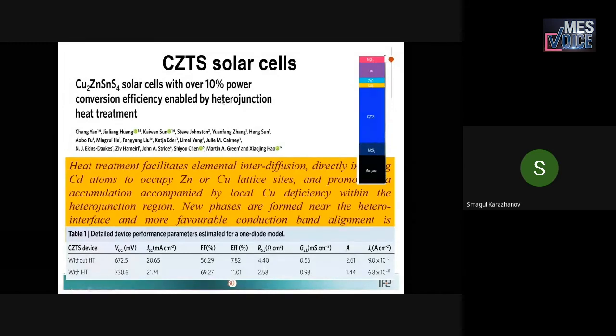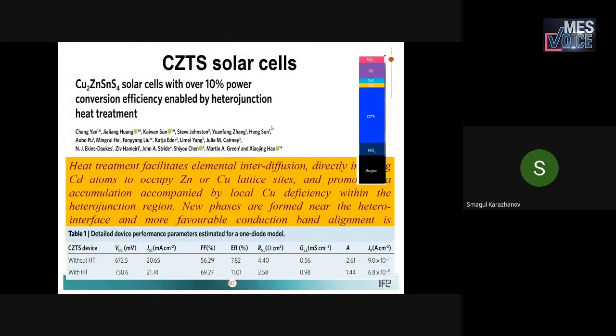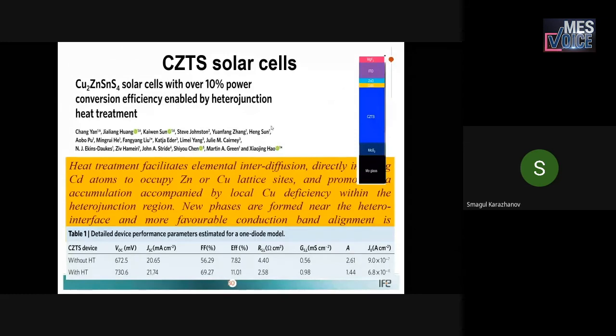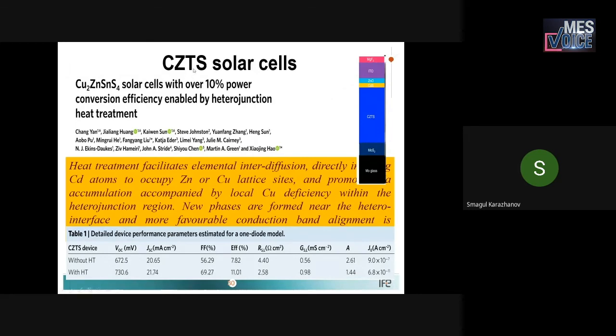And then another interesting solar cell is CZTS: copper, zinc, tin, sulfide. And efficiency is too low for this type of cell. It's about 12.6% today. Still, this is much lower than the 32% predicted by theory. So the research is ongoing about this solar cell.